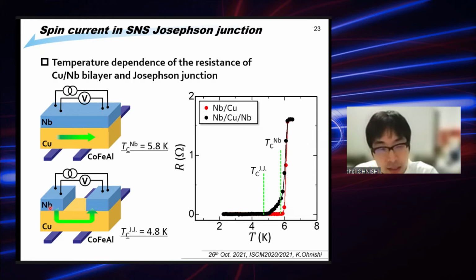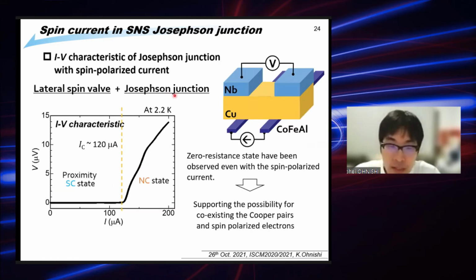In the case of the junction, below 4.8 Kelvin, the junction showed zero resistance. So we succeeded in the fabrication of the Josephson junction, the niobium copper junction. By using these samples, we measured the IV characteristic of the junction.